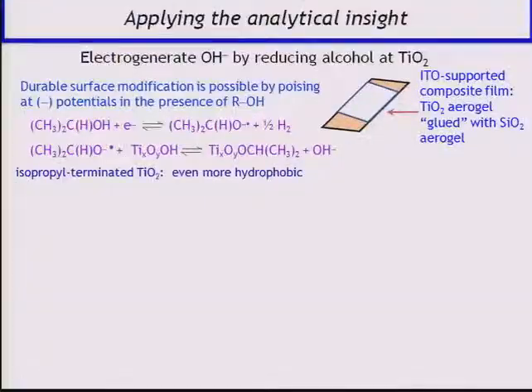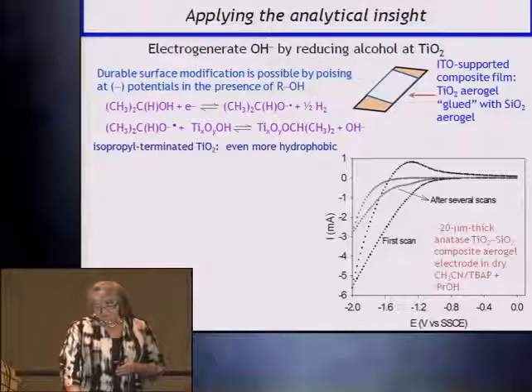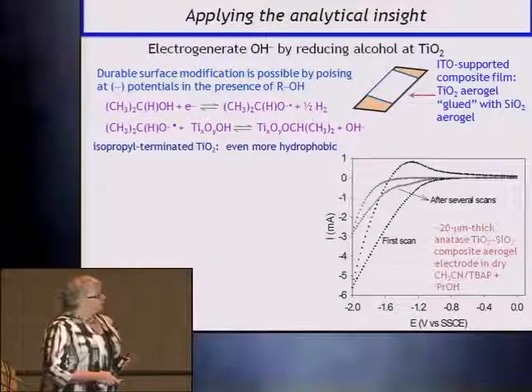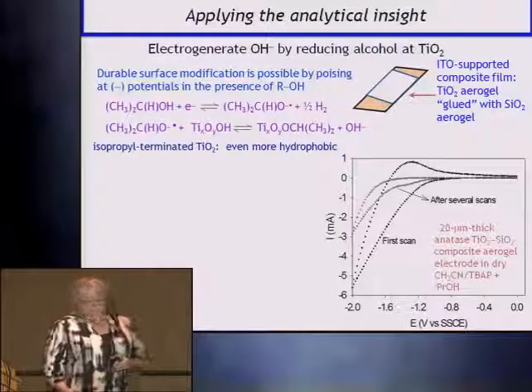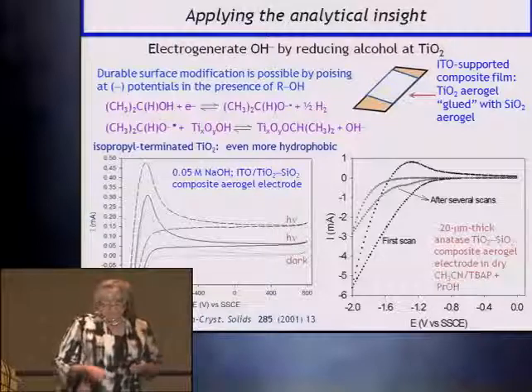It was obvious with the aerogel. It took a little bit more time with other forms of titanium. But you can undo sol-gel chemistry, particularly if you get too much water in the system. So we also recognized that we could electrogenerate, shall we say, a better reactant. In this case, the anion radical form of isopropanol, the isopropyl radical. And again, you completely make this very hydrophobic, and the performance enhancement you get.